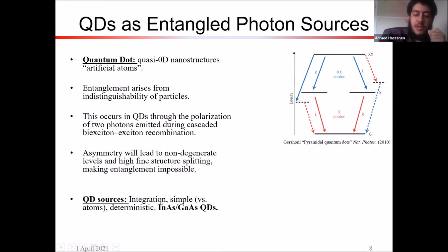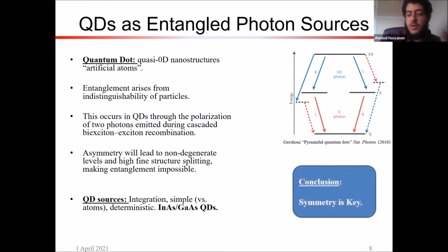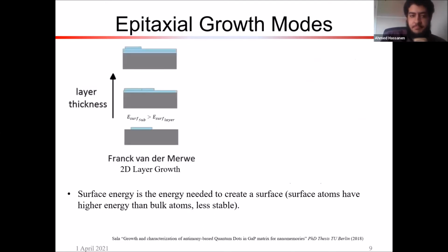And quantum dot sources for entangled emission are actually pretty advantageous because they're easy to integrate with the current mature semiconductor processes that we have. They're simple as opposed to atomic sources, for example. No need for this trapping and stuff. And it's deterministic. So with a photon trigger to trigger this cascade, we can get the photons. And basically, indium arsenide, gallium arsenide quantum dots are the main material system to realize these types of entangled photon quantum dot sources. And so the conclusion here is symmetry is key.